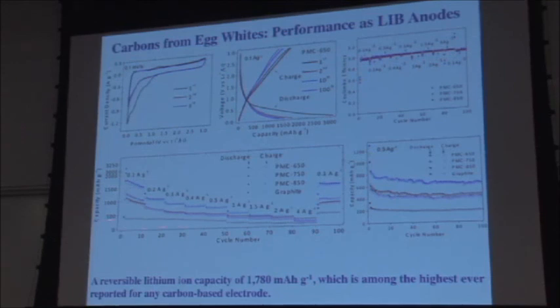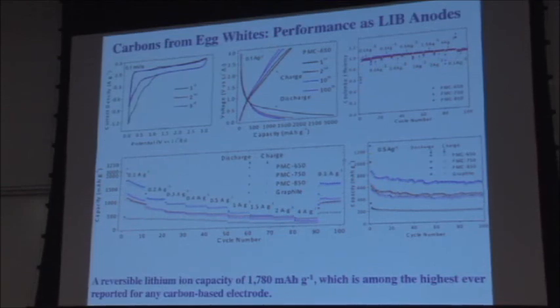When we cycled it, we included commercial battery-grade graphite as an electrode baseline, cycled at different current densities. Of course, at the higher current densities, it has less capacity, but you would expect that for any kind of electrode material. But then after the cycling, when you go back to low current density, it springs back pretty close to the original value. And if you look at the cycling performance at 0.5 amperes per gram, it's just as stable as graphite in terms of capacity retention after 100 cycles. So this reversible capacity is quite high by literature values.